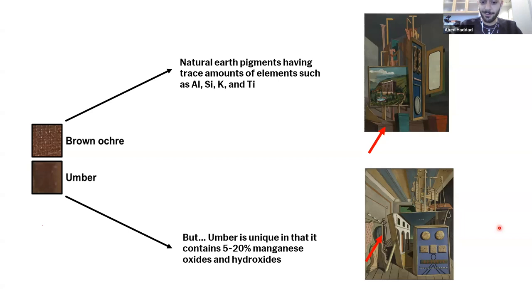However, some combination of elemental markers and the color of the paint applied can help suggest the type of brown used. So for example, iron-based browns are all characterized by high levels of iron, with some natural earth pigments having trace amounts of elements such as aluminum, silicon, potassium, and titanium. So ochres tend to be very rich in those materials. So you can see here, for example, a brown ochre was used in this Great Metaphysical Interior painting in the pedestal or base. However, umber is unique in the browns in that it contains 5 to 20% of manganese oxides and hydroxides, and the presence of manganese in an XRF spectrum can help us pinpoint the use of umber, for example, here in this bolster in Biscuits.